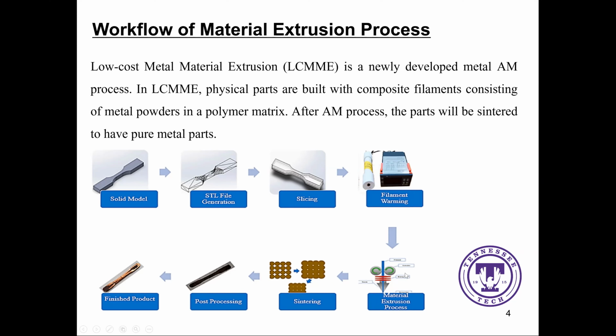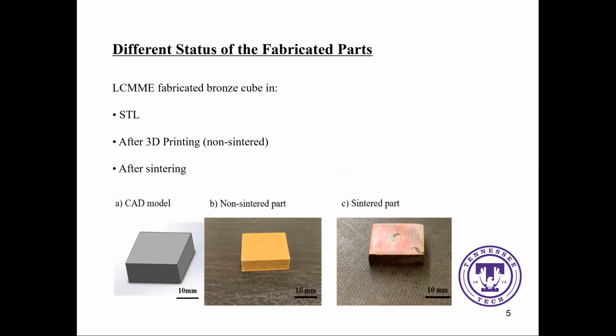But after the 3D printing, we have a sintering process. After the sintering process, the final part is a pure metal. For example, in this research, we use a bronze PLA material to do the manufacturing. The first is the STL file generated on the SolidWorks, and we get the G code to do the 3D printing. In the middle is a non-sintered part. It's a mixture of bronze and the PLA. And after the sintering process, the final part is pure bronze. The PLA is melting out in the sintering process.